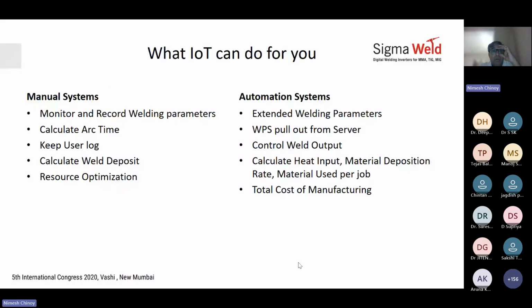What IoT can do for you for manual systems that you're using for manual welding: you can monitor and record the welding parameters. That means you could measure the welding current, welding voltage, gas flow, wire feed rate. These are basic welding parameters. You could calculate the arc time. How long was the welder welding? The equipment was on, arcing for how long? You would keep a user log. That means which welder was welding at what time, with what parameters.